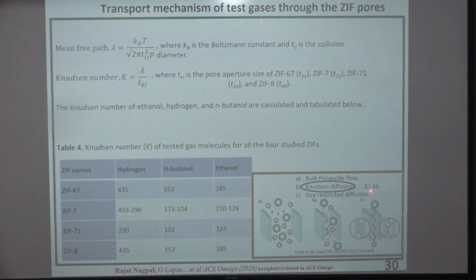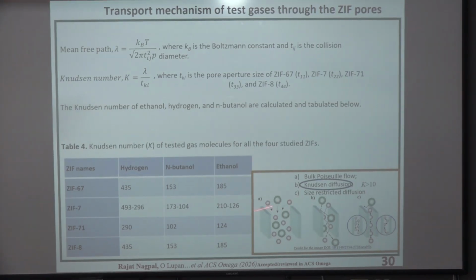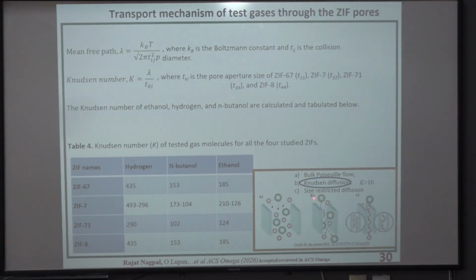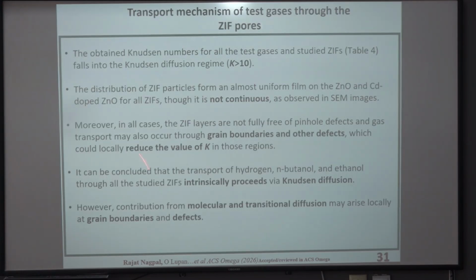Yeah, we did not go into a detailed defect investigation, but the reason I am saying this is that these numbers are far higher than 10. According to this calculation, if k is greater than 10, then it falls in the Knudsen diffusion regime. If there is a contribution from defects or grain boundaries, the value of k will decrease. But even if it decreases, it will take far to reach 10. So most prominently, intrinsically it proceeds by Knudsen diffusion, but we cannot say 100% it is due to Knudsen diffusion. Maybe a contribution may come from molecular or transitional diffusion as well. Thank you.